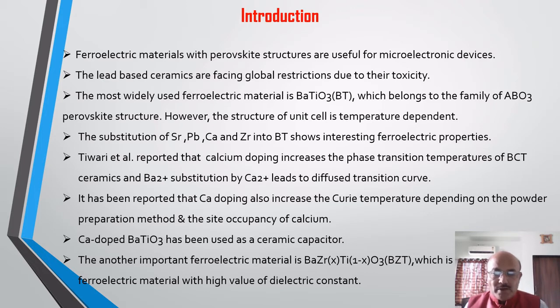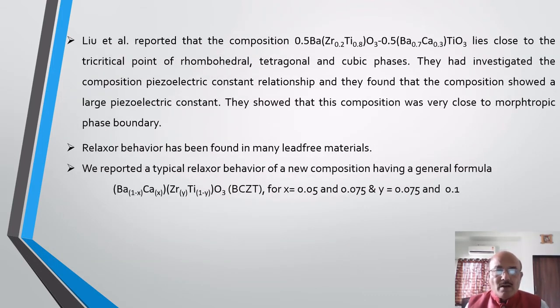Another important ferroelectric material is BaZrxTi1-xO3, that is BZT, which is also a ferroelectric material with a high value of dielectric constant. Liu et al. reported that the composition 0.5 BZT, 0.5 BCT lies close to the tricritical point of rhombohedral, tetragonal and cubic phases. They investigated the composition piezoelectric constant relationship, and they found that the composition showed a large piezoelectric constant. They also showed that the composition was very close to a morphotropic phase boundary.